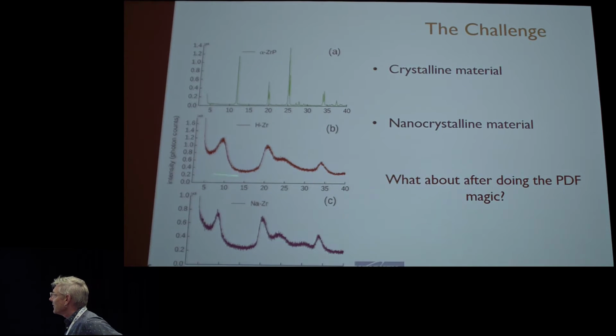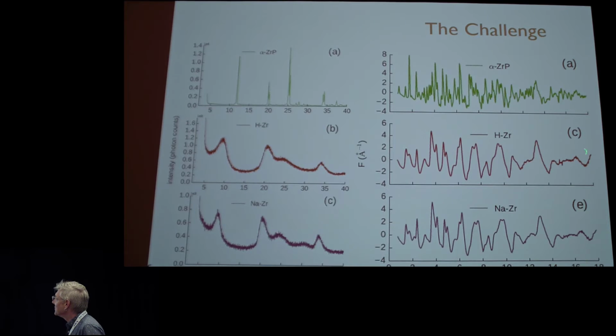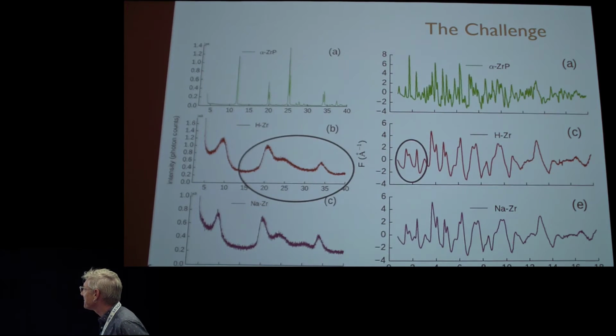All right, so the challenge was that we had less information and we needed to solve a more complex structure. And what we've done is we've devised a slightly different experiment where we've got an enhancement in the information. So what happens to this diffraction pattern when we put it through that PDF approach? And it looks like this. So again, from an information theoretic point of view, we have much more information back again to play with. In fact, this thing that we saw down here is actually this part of the diffraction pattern.